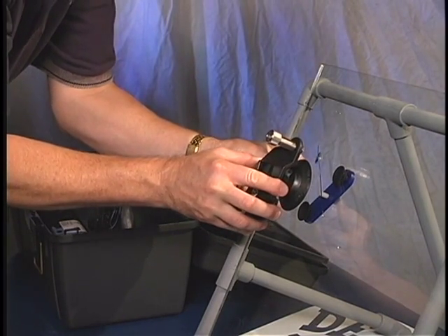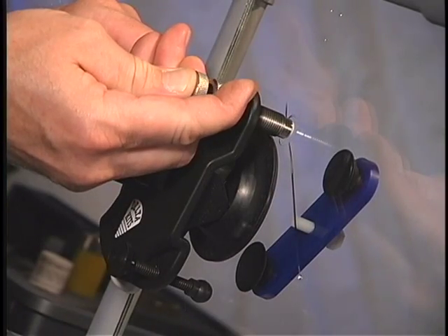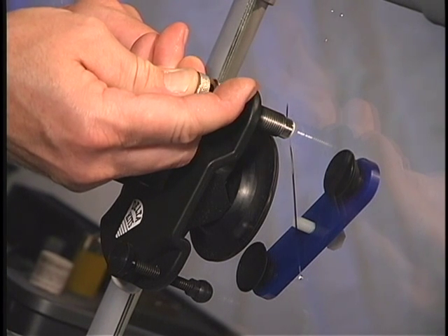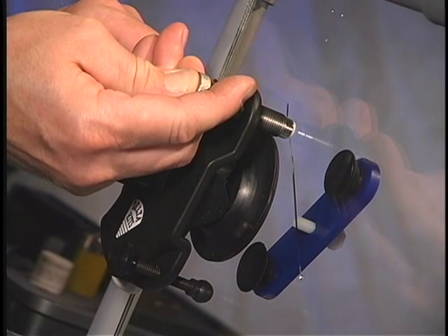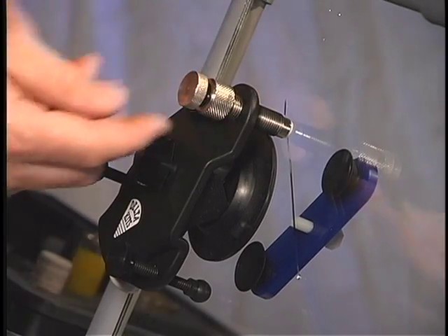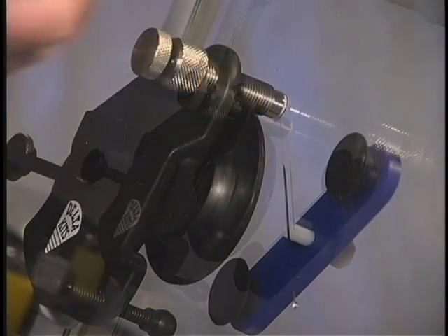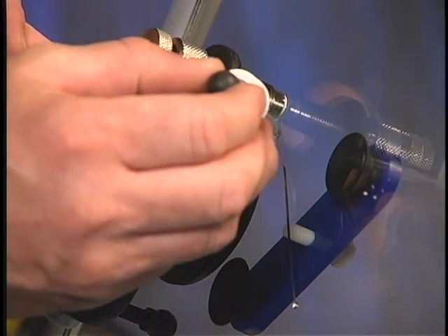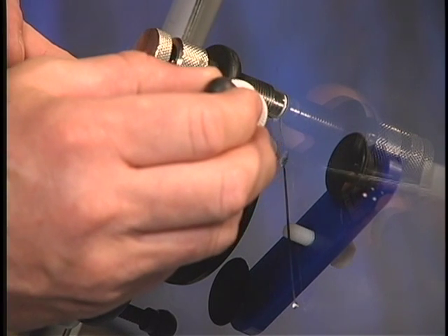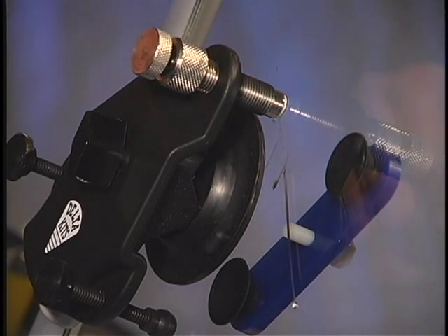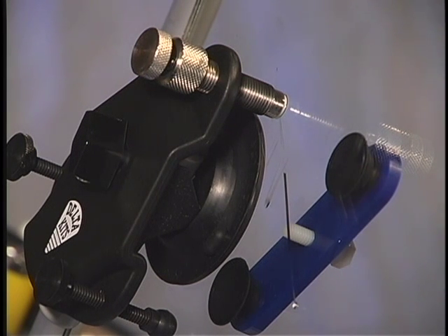As the resin is injected into the break, the crack will usually fill to a length of 1 to 1.5 inches. When it appears that the filling process has stopped, usually about 5 minutes, place a drop of resin about 1/16 of an inch behind the farthest point the resin has reached. The pressure created from the injector will continue to push the resin out into the crack another 1/4 inch to 1/2 inch.